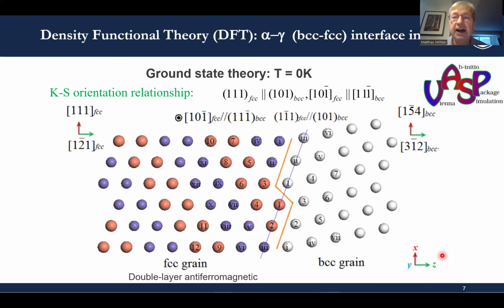We have to keep in mind it's a ground state theory, so we are at 0 Kelvin. It's computationally very expensive, so even with our much developed computational resources, we can typically only do calculations with a few hundred atoms. If you want periodic boundary conditions and an interface in the simulation domain, we have to find special interfaces that have a periodicity that fits into the simulation box. Here for the alpha-gamma interface, we found a Kurdjumov-Sachs orientation relationship that fulfills these criteria. If you look at grain boundaries, we are typically restricted to low sigma grain boundaries, sigma 5, sigma 13, etc.